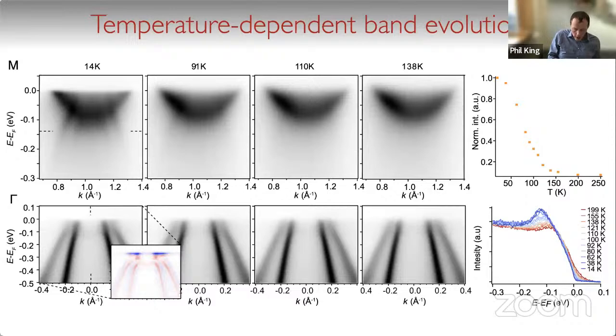Now we can also look at the gamma point, and we see here that in fact we also have a rather strong band reconstruction, where you can see a slight buildup in the middle here, and you can see this also in energy distribution curves. As we lower the temperature, we have a buildup of spectral weight at the gamma point, which is due to the conduction bands now backfolded from the M point to the gamma point of the Brillouin zone.